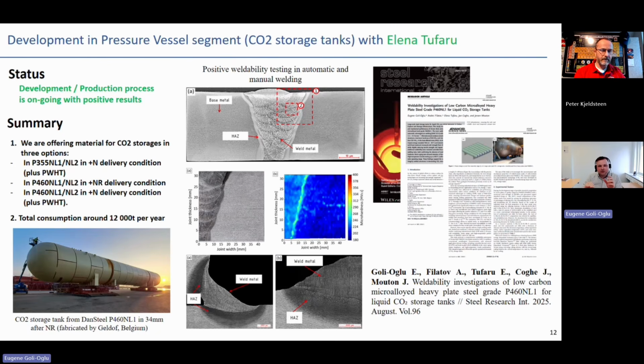And then when they reach certain temperatures and the energy level is at a different stage, you start to deform and make some pancaking of these grains and make smaller defects, dislocations and others in these grains. And then later, when there is the final transformation of material from austenite to ferrite or bainite, or acicular ferrite, which is the best in this case, those small dislocations, small defects and grain boundaries will become places where new grains will be born. And depending on their size, you get the final size of your grains inside the steel.